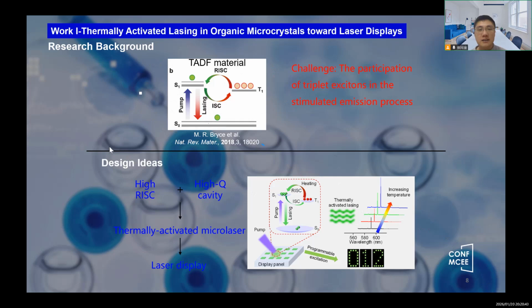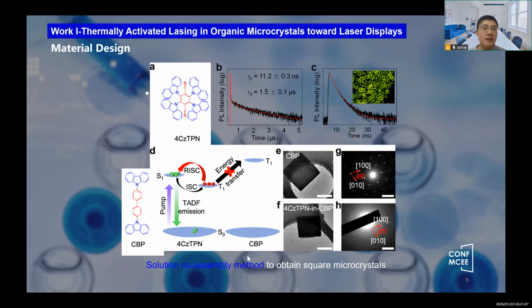Therefore, we select TADF systems with high luminescence efficiency and high RISC efficiency based on laser theory, and combine them with high-quality microcavities to achieve thermally activated laser emission. With the TADF material adopted, CBP microcrystals were obtained through a solution co-assembly method. Selected area electron diffraction confirms that the introduction of TADF molecules didn't significantly affect the structure of the CBP microcrystals, maintaining excellent crystallinity.